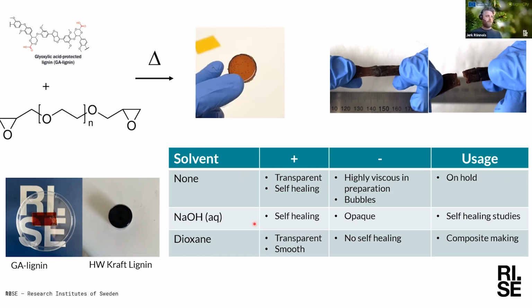We also played around with using aqueous sodium hydroxide solution, which dissolves the lignin very well and actually yields a self-healing elastomer. This is what you see on the top here. We will be discussing those more in detail later on. It's not as nice. It's opaque and it looks a bit more messy than these transparent ones. But we will continue studying the self-healing properties of this.